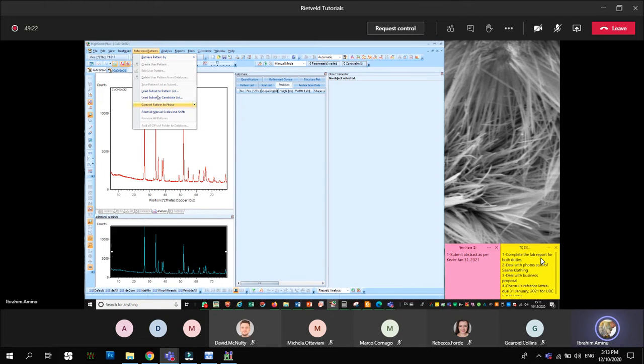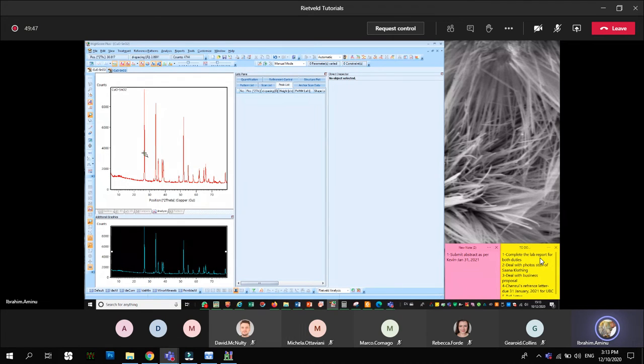These are just to eliminate maybe the minor peaks that in your fitting will not yield any phase. So for example, if I want to find the phases here, typically based on the material I prepared, I'm expecting copper oxide and tin oxide. But here, do we see these peaks or what? You are not very sure of these things. Sometimes we are not sure if they are peaks or from the instrument or whatever.